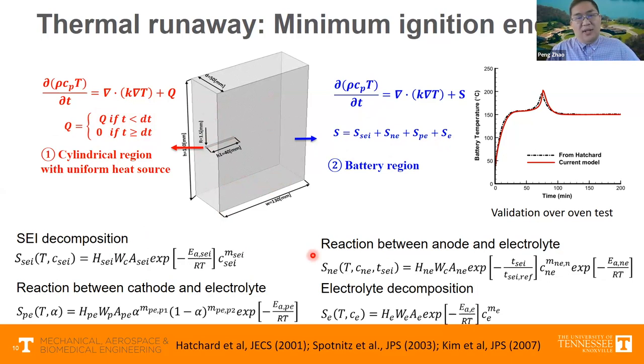Compared with the very mature detailed chemistry of fuel combustion, the chemical kinetics of the thermal runaway is still sort of in the infant stage. We're still using very global reaction source terms to represent, for example, SEI decomposition heat source, the reaction between the anode and electrolyte, reaction between the cathode and electrolyte decomposition. And more recently, there have been more complicated thermal runaway mechanisms, including the effects of binder and other stuff. But still, it's not at the detailed level, it's at a semi-global level. So these parameters from these reactions can be largely quantified from the differential scanning calorimeter experiment. As you can see that with the appropriate parameters, this model can agree with certain experimental conditions pretty well.